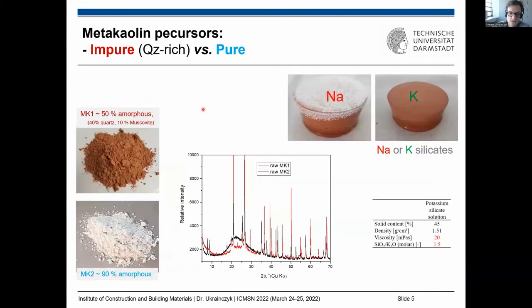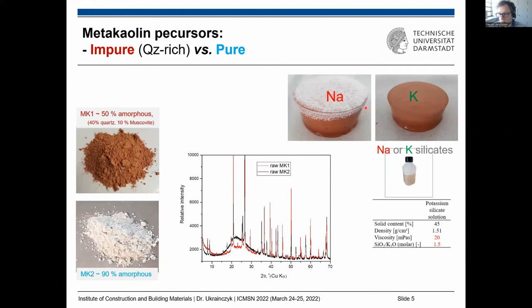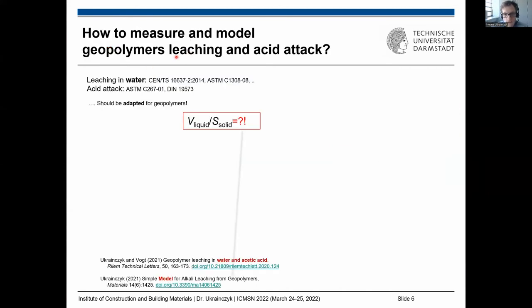For the geopolymer raw materials: metakaolin clay can be impure and quartz-rich, or we can use a very pure white clay. X-ray analysis shows the amorphous metakaolin — that is, the dehydroxylated clay. The second component is potassium silicate. We use potassium rather than sodium because this reduces the amount of alkali leaching, which would otherwise carbonate upon CO2 exposure and cause efflorescence.